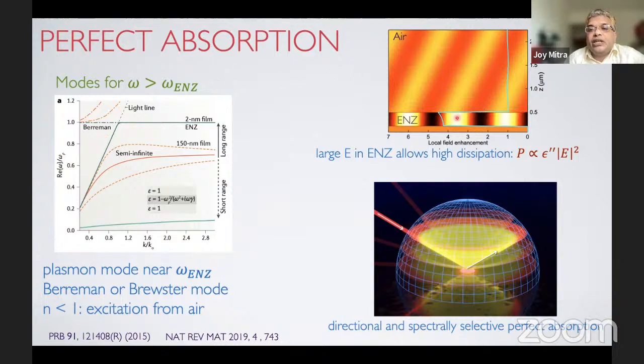Not only that, if you look at the calculated electric field, you see the electric field is highly enhanced and trapped within that ENZ material thickness. And therefore, it allows for high power dissipation, because power dissipation goes as epsilon double prime times E square. Epsilon double prime is small, but E square more than makes up for it. That very large enhancement in electric field locally absolutely makes up for the deficiency in epsilon double prime. So even though the films are not very lossy, we actually get a very large power dissipation.